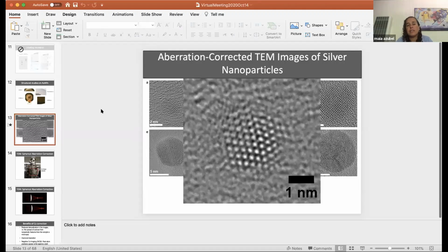So the honest answer is, and we can say the same for any method, how do we know that when we crystallize, we are not changing the crystal constants? The truth is, there is a possibility that just by putting the clusters in the microscope, you are changing them. The one thing that I did is I took images at a dose that allowed me to take two consecutive images to make sure that nothing was changing. If something happened very, very fast, I cannot detect it. But I was trying to be as careful as possible, working with the minimal dose possible where I still see signal, but don't see a change in the overall structure.